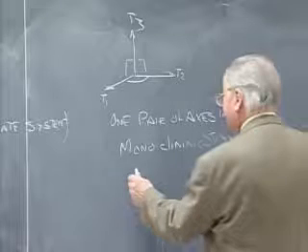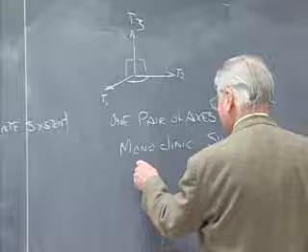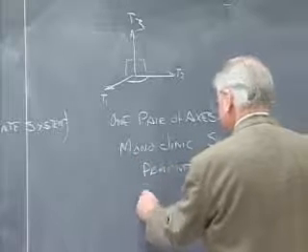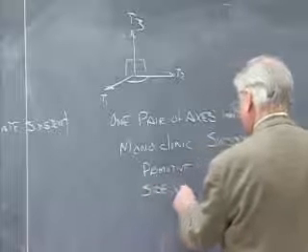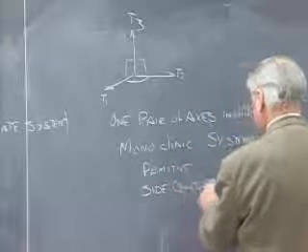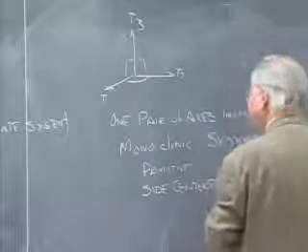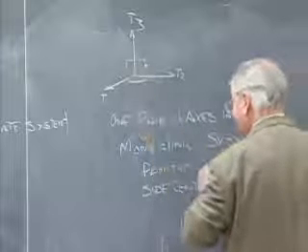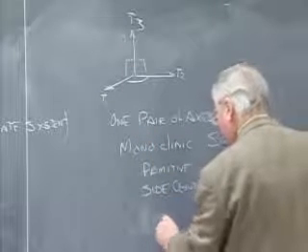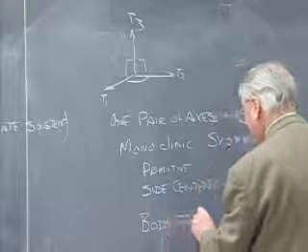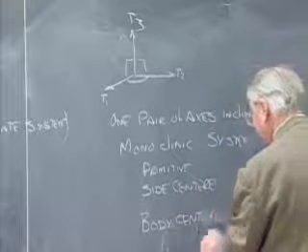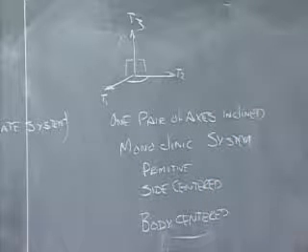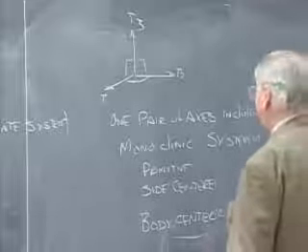And this can contain lattices that are either primitive, side-centered, with either the longest or shortest translation in the parallelogram net coming out of the face that's centered, or we saw there was one final possibility, and that was body-centered. So we'll refer to these lattices subsequently as monoclinic primitive, monoclinic side-centered, or monoclinic body-centered.